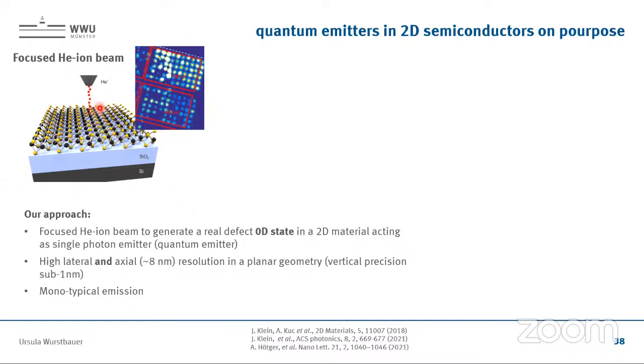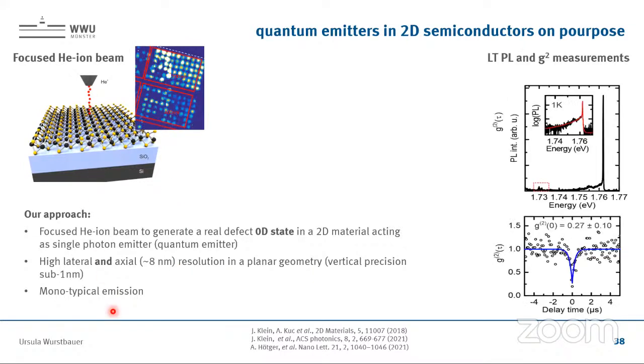And since it's in a defect state, it's a monochromatic emission. So you can also check here, that's the peak, it's ultra narrow at low temperatures. And then you can measure the autocorrelation function, it's done here. So you see this nice dip, it goes well below 0.5. So from that point of view, check the box.